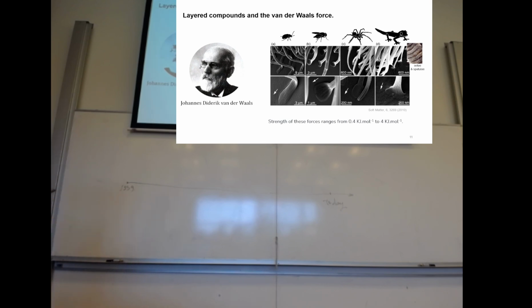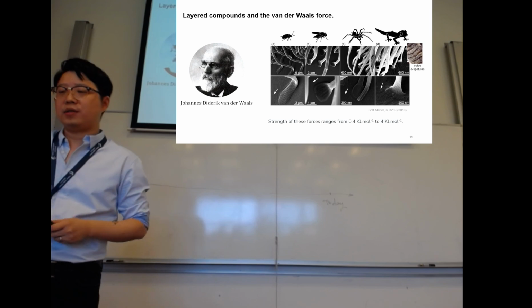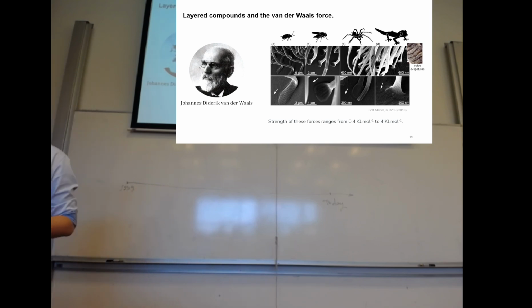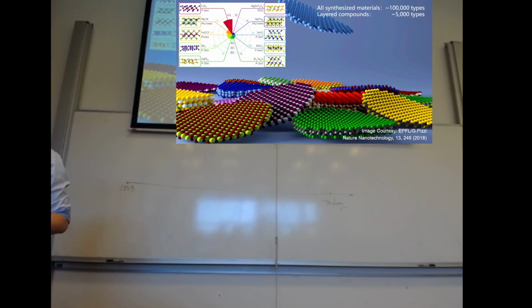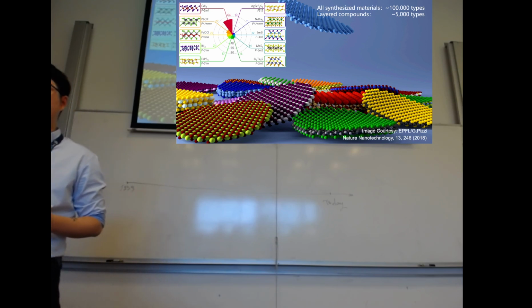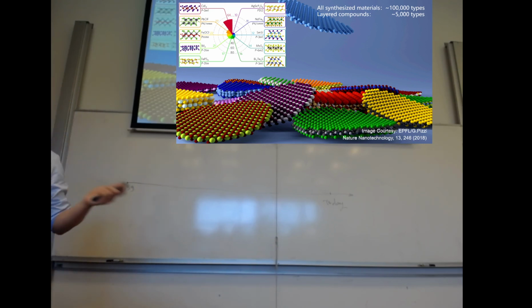So this is how the whole story was seen at that time, and we can have an estimation of the strength of these forces. They range from 0.4 kilojoule per mole to 4. That is 1 or 2 orders of magnitude lower than chemical bondings. So very weak. People can break them by hand. And also, if we take a broad view of all these compounds of layered structures, already now people have more than 5,000 types fabricated experimentally. So there are so many options for us to choose.